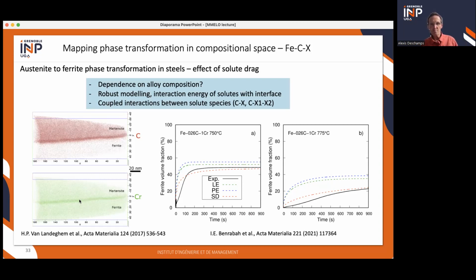This can be substitutional species such as chromium here, or carbon, or both in this case. And this solute, while the interface is moving, is exerting a solute drag, and this changes the kinetics quite a lot. So here, for instance, is an experimental kinetics of phase transformation in two different conditions on the same steel containing carbon and chromium. And you can model the kinetics only by solute drag. If you look at other thermodynamic conditions such as local equilibrium or para-equilibrium, then you get kinetics which are much faster than the experimental ones.